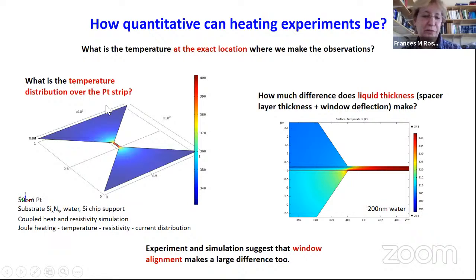We need to know what the temperature actually is. And this is typically being addressed with finite element calculations. So here's the heat distribution on one of these little platinum strips. And here's the heat distribution vertically in the sample. The heater is only on one side, and you can see that there's actually a gradient in heat from the hot to the cooler part as you go vertically. So this would favor reactions maybe on the electrode that was close to the heater.